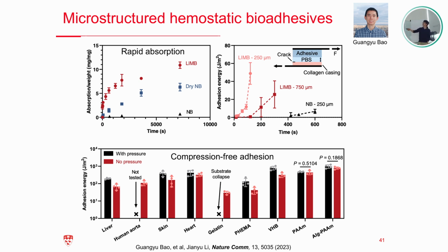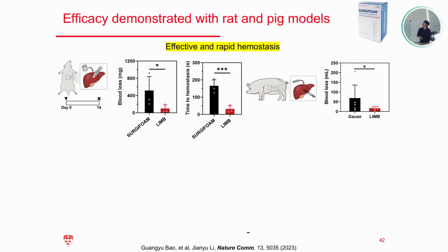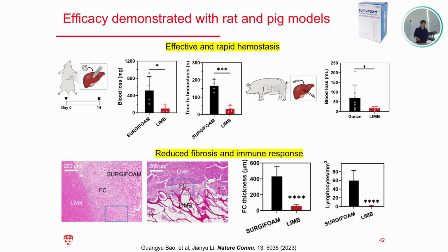In this case, the blood can be removed by capillary effect. We don't apply compression, so we tested in different systems without compression, and we get a reasonable adhesion performance. So efficacy has been tested in a mice model. We're also testing in the pig, and we compare with clinically used products such as Surgifoam or simple gauze. We achieve much less blood loss, faster hemostasis, and most importantly, compared to Surgifoam, we achieve much better biocompatibility by reducing the fibrosis level and triggering much less immune response.